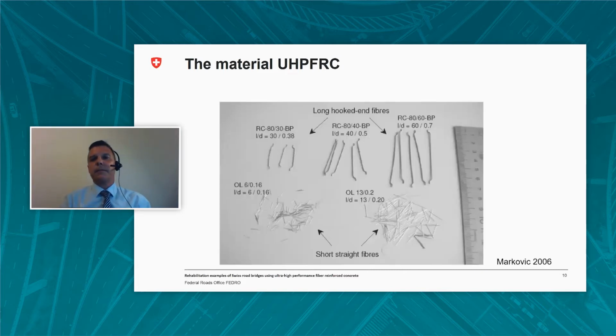fibers. They are characterized by the material, by its mechanical properties and their geometry. In order to enable the transfer of force with a small crack opening and to sustain tensile forces without breaking, a high modulus of elasticity and high strength are required. The modulus of elasticity of steel fibers is 200 gigapascal, and strengths are in the range of 1,000 to 3,000 megapascals, with a deformation at failure of about 3 to 4%.